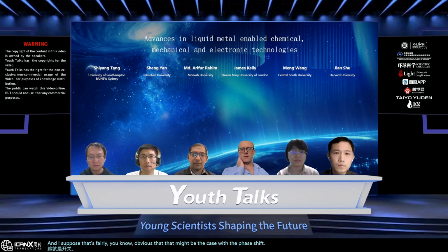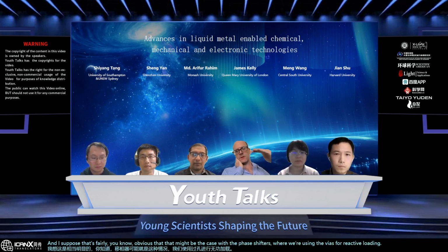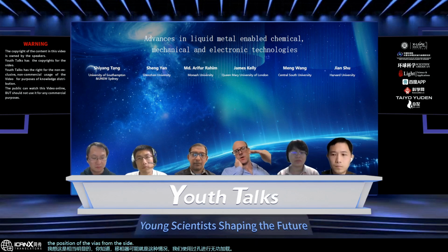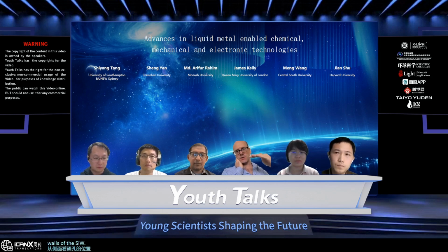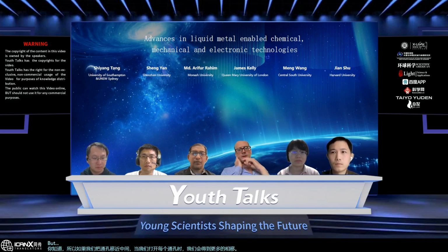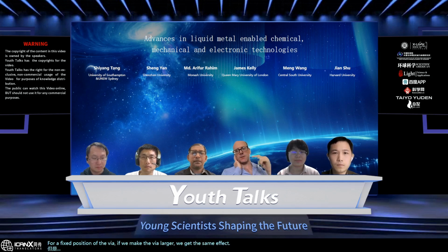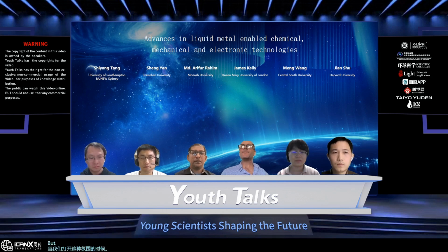With the phase shifters, where we're using the vias for reactive loading, the position of the vias from the side walls of the SIW determines the extent of the phase shift that we get. So if we move the vias closer to the middle, we get more phase shift when we turn each via on. But for a fixed position of the via, if we make the via larger, we get the same effect. In other words, we get more phase shift when we turn that via on. But the negative side of that is, whilst we get more phase shift from that particular via, we also get more reflection from it as well.